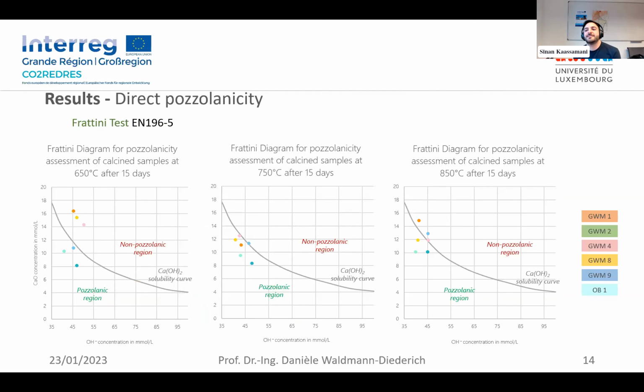And then we have the Frattini test, which was performed as well for 8 and 15 days. So here I'm presenting only the 15 days results. This is a method based on titrations, and it's used to determine the amount of dissolved ions, so calcium and hydroxide ions in a solution containing the tested pozzolan. So of course at 20%, the same amount that we substituted for the OPC. And then we can see the pozzolanic region is the one that's under the reference curve. We can see that many of our materials are already pozzolanic at 650 degrees, but then at 750 degrees as a temperature for treatment, we already have all our materials in the pozzolanic region.